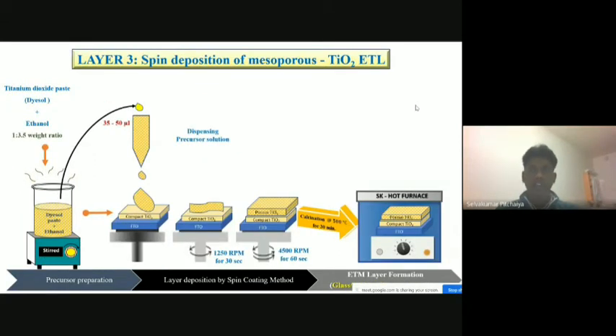And this is another porous TiO2 layer, where it allows the perovskite layer to incorporate inside and enhances the charge mobility in the perovskite layer. This layer is deposited using spin coat deposition, with a two-step spin deposition. The first step makes the solution spread all over the layer, and the second removes the unwanted, undeposited solution over the film. And finally, we anneal it. We anneal at 500 degrees Celsius to form the mesoporous TiO2 layer.